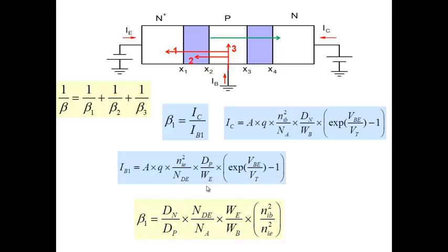And we take the ratio, and in this expression, note that what I have done deliberately, even though both emitter and base are silicon, is to write Ni in the base as NiB square, and Ni in the emitter as NiE square here. Although both materials are silicon, we'll show you in a minute that doping has an effect on the effective band gap, and it changes Ni here.